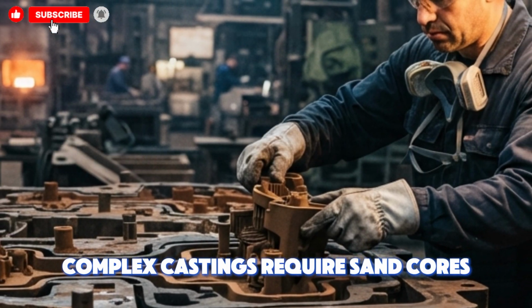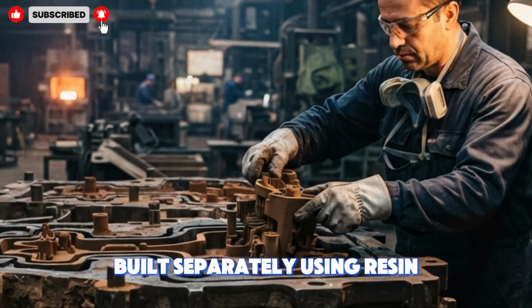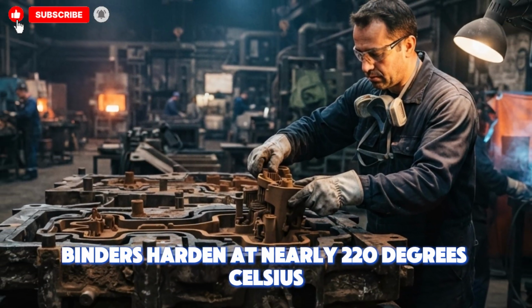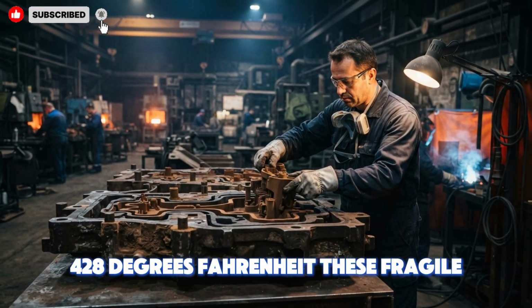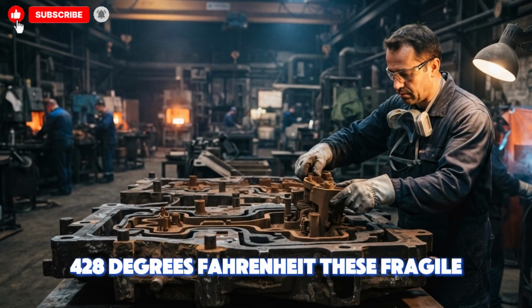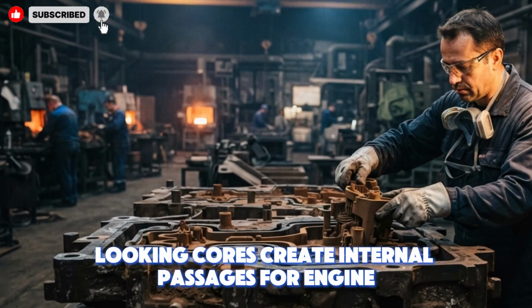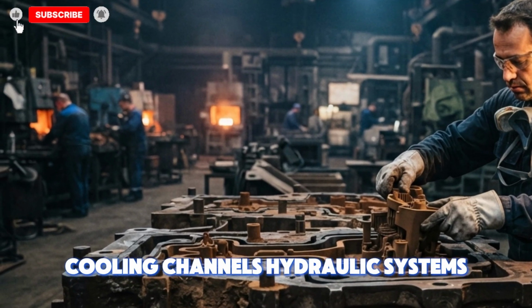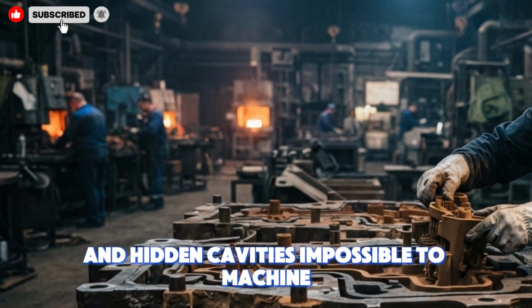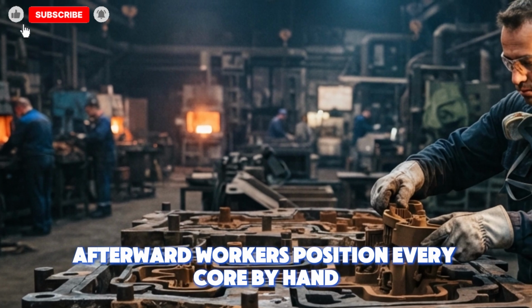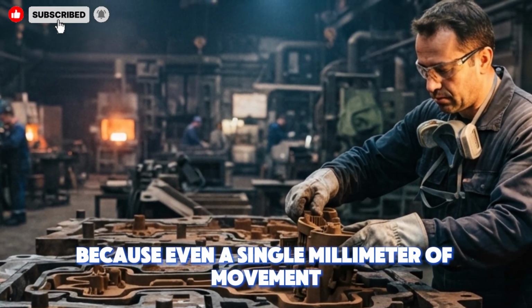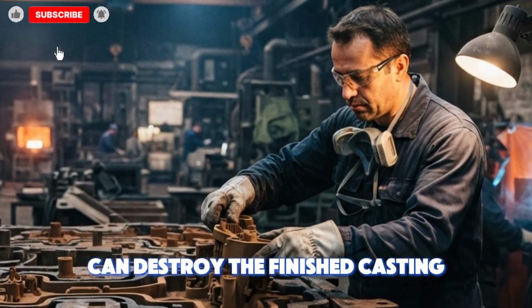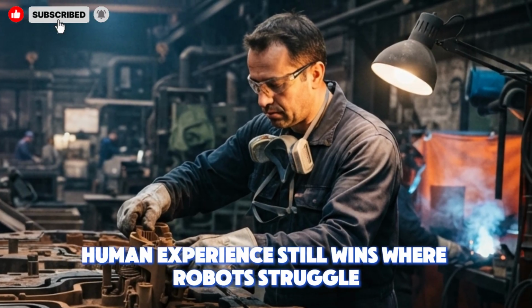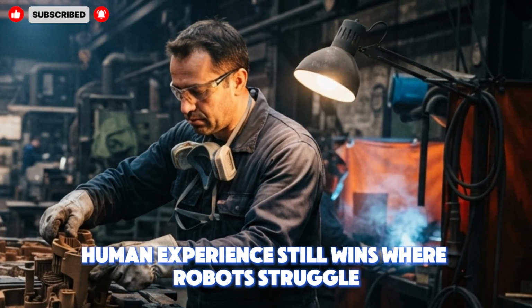Complex castings require sand cores built separately using resin binders hardened at nearly 220 degrees Celsius, 428 degrees Fahrenheit. These fragile-looking cores create internal passages for engine cooling channels, hydraulic systems, and hidden cavities impossible to machine afterward. Workers position every core by hand because even a single millimeter of movement can destroy the finished casting. Human experience still wins where robots struggle.